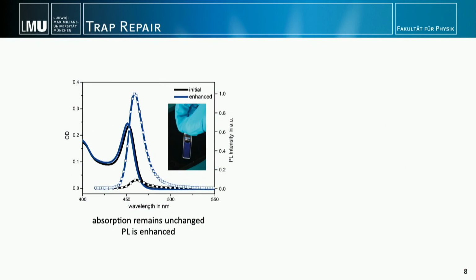As a quick add-on, I want to show you that adding lead bromide to the previously prepared sample does not change the absorption at all. This is shown on the left side. So the absorption spectrum stays the same, only the PL gets enhanced. In this example, I think we see the 2 monolayer sample where it's enhanced by almost a factor of 8.